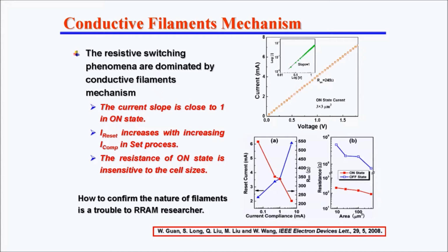metrology. At the beginning, we say one device fabricated with the low resistance states, the slopes, we can say they're close to 1. That means in the low resistance states, it's similar to a metal. They behave like a metal. Also we use different compliance currents to trigger this device. Then we measure the reset current's relationship with the compliance current in the set process. We can see this relationship is also similar in the low resistance states. They behave like a metal.